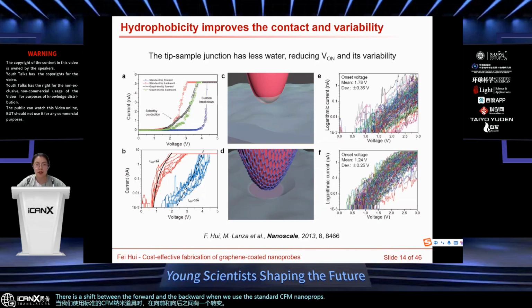This shift is caused by the potential because of the existence of water molecules between the tip and the sample. When we use the graphene coated tips, we see a real resistance, and the forward and the backward sweeps overlap. This statistical plot further confirms the low variability obtained by the graphene coated tip.